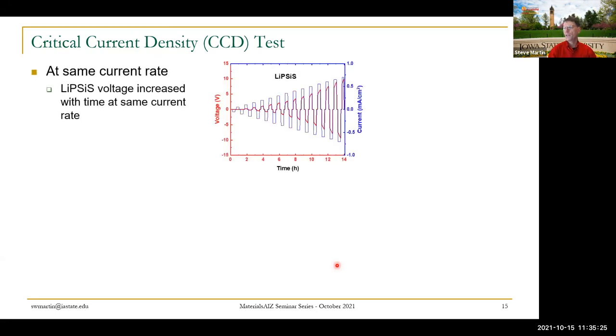In these plots, I've got again a lithium metal glass. I've got lithium metal on both sides. I've got glass in the middle. And I'm simply applying a voltage across those. I'm using the lithium metal as a metal anode and doing two things at one time. I'm creating a voltage across the lithium metal. And the only thing that can happen is the lithium ions flow through the cell. And the higher the voltage, Ohm's law says, the higher that lithium ion current should be. And that's what's shown here.